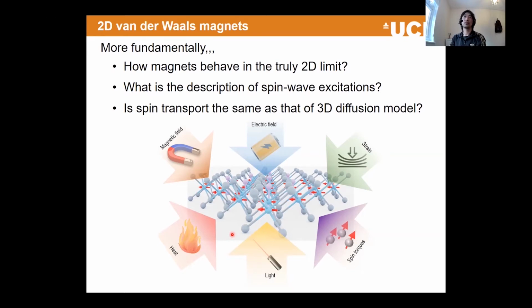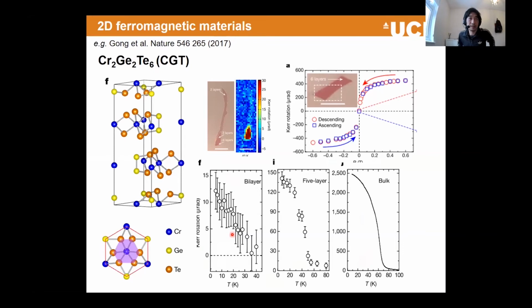So these are a few things that we want to do in the next few years, or even within 10 years. Now, what exactly do we have so far as a menu of 2D magnetic materials? I just want to introduce two famous ones. Number one is chromium germanium telluride. This is the stacking of layered films, and this is a top view of it. The blue one is chromium, which carries angular momentum. Then through these tellurium atoms, we can have so-called super exchange coupling between the chromium atoms.